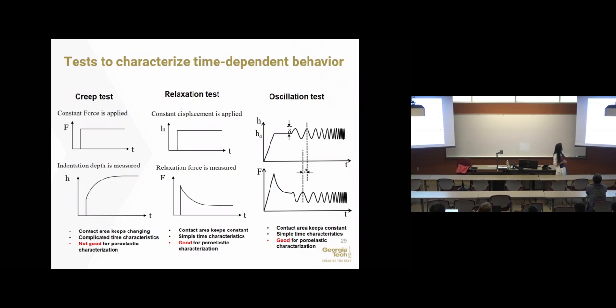Looking at methods to characterize time-dependent behavior of gels, there are several widely used methods like creep test, relaxation test, and oscillation test. Actually, the creep test is most widely used because it's force controlled. The equipment is naturally built that way. But it's not a good method to characterize the coupled deformation and diffusion behavior of gel, for the following reason. In a creep test, we apply a constant force and measure the indentation depth as a function of time. As the indentation depth changes, the contact area also changes. And the time scale of this problem is defined by the diffusion, and the diffusion is related to length, which is the size of indentation. As your contact radius keeps changing, your characteristic time keeps changing. It's very difficult to get a clean solution out of it.